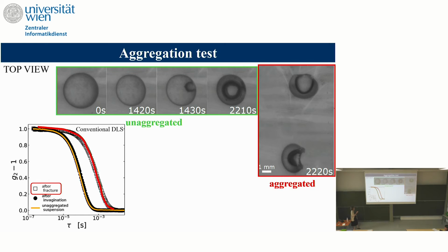So at a certain time, in all this green zone, you take the drop and put it back in water, and check what you have. All along this process, even here, when you have this instability that we see, you have this data, the black data, underneath the yellow curve. So you don't have any aggregation. It's fully dissolved. There's no evidence that you have something solid. Everything is fully dissolved.